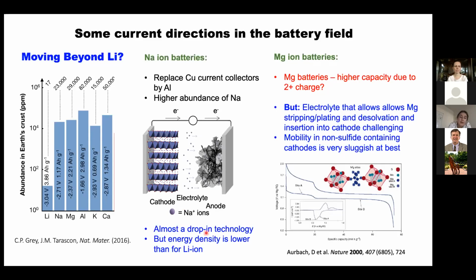And it's been surprisingly easier than people thought, and it's almost a drop-in technology. But one of the challenges is that you can't use graphite, because you can't intercalate sodium into graphite. And so the challenge is to come up with these so-called hard carbons to do the work.